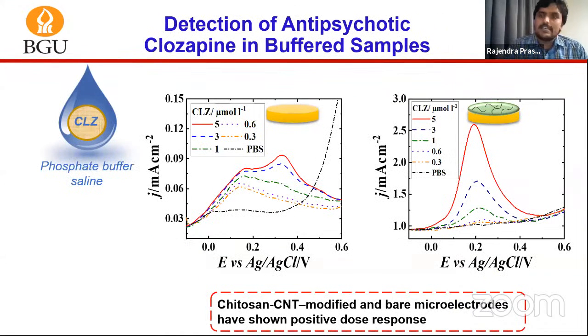So here on the screen, you see the detection of clozapine in 20 microliter volume of buffer sample, which was spiked with these levels of clozapine. This is showing the recorded differential pulse voltammogram, which records the oxidation of the specific redox molecule, using bare gold microelectrode. And this is showing you the differential pulse voltammogram recorded using chitosan carbon nanotubes. Here in this picture, you see there are 2 peaks. The first peak is because of the byproduct of the clozapine. That is from the literature that we took. And here it is the oxidation of the clozapine. With the chitosan carbon nanotube modified microelectrode, you see a clear and distinct peak used for the clozapine oxidation.